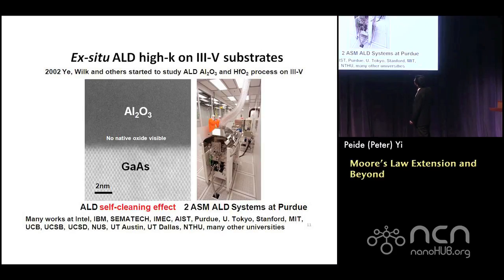So this is the example. We realized at the very beginning, with high resolution TEM, you really can zoom in and look. After growth using the atomic layer deposition technique, which I will explain in the next slide, you can grow the high quality amorphous oxide on top of the gallium arsenide without any visible native oxide. Later on, we understood that we call it a self-clean effect.